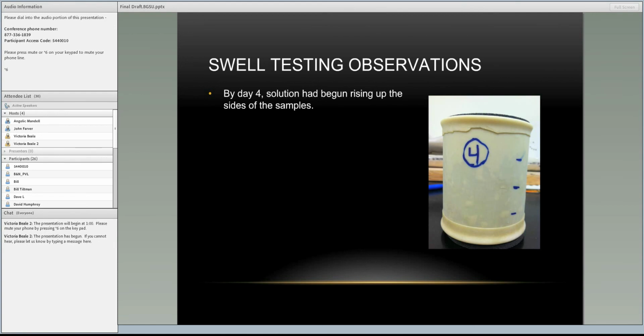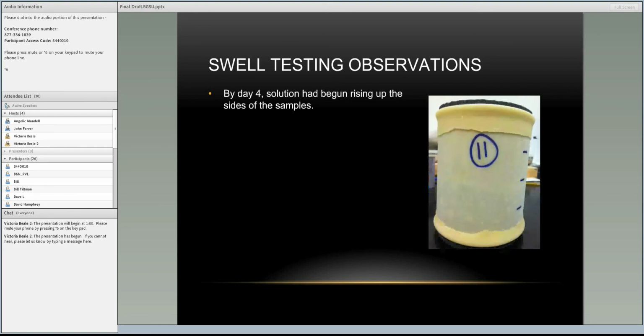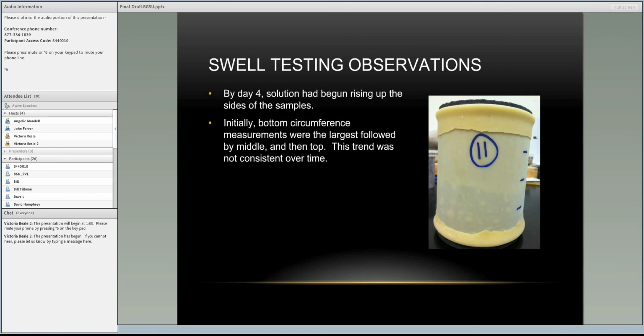Initially, when looking at the circumference measurements, when measuring the bottom versus the middle and the top, the bottom measurements were the largest, which makes sense given how the moisture was rising through the sample, followed by the middle and the top, but over time that proved not to be consistent. This could be due to a number of reasons, primarily because there started to be cracking as the swelling continued. And like I said before, in general, the dry samples swelled slightly more than the wet samples, and the sulfate slightly more than the distilled water samples, but again, not a lot of significant difference between those.